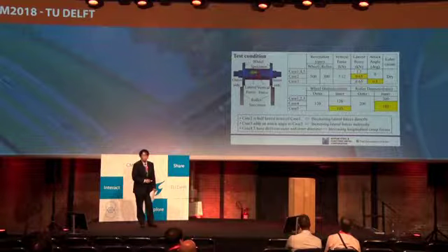And case 3 adds an attack angle to case 2. This is aimed at increasing lateral forces indirectly. And case 4 and case 5 have different outer and inner diameters. This is aimed at increasing longitudinal creep forces.